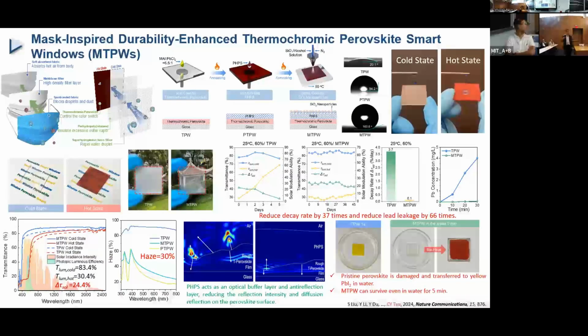So similarly, we also have 2 more layers. The outer layer is to repel the water droplet. The middle layer is to allow a certain vapor to transmit, because we need the water vapor to react with the perovskite material such that perovskite can conduct the exchange. So we do not want to have any water droplet. We indeed need to have some water vapor.